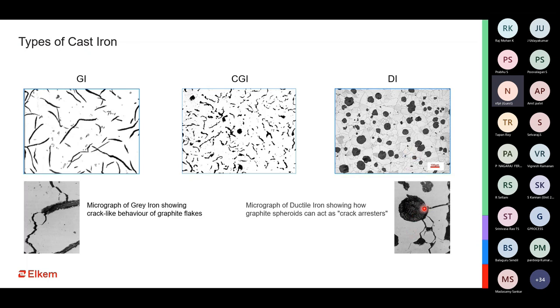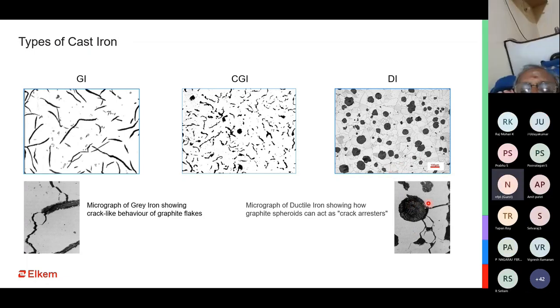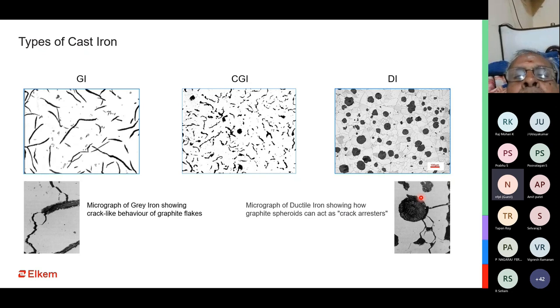And because it takes some time before it actually allows the crack to propagate, that is the period where the elongation happens, or the casting becomes longer before it breaks. That's a very crude way of explaining what elongation means. This is why ductile iron castings also have some percentage elongation, or change in shape, before they actually break, which gives them a better mechanical strength, that is tensile strength, as well as a better ductility, that is the percentage elongation.